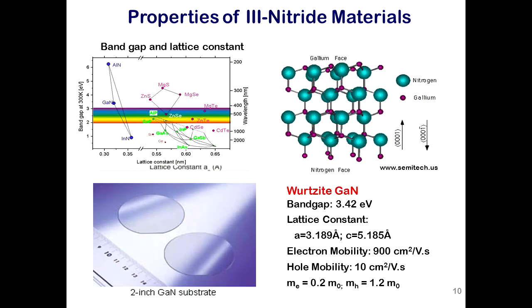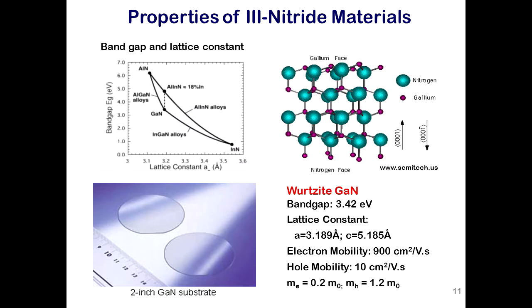So these are hexagonal crystals, these three nitrides, and you can see that they are smack in the middle of the visible range. So one uses these alloys, indium gallium nitride, to get all the visible colors. And that's the nitride system in more detail, the binaries and then the ternaries and quaternaries in between. And so it's a hexagonal structure, and these are some of the fundamental properties. And just to give you a calibration,